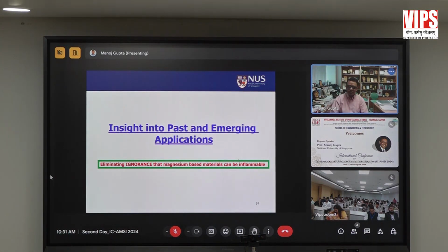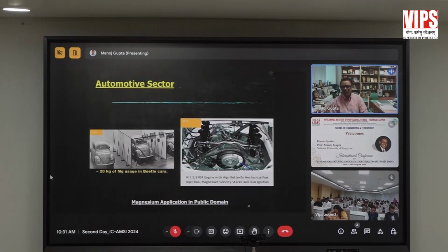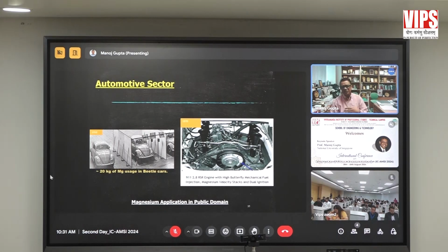Now, people used to say, or were under the impression, that magnesium can catch fire because when we were in school, we used to burn magnesium ribbons and magnesium powder. But that is not true when you use magnesium in the bulk form. And I'll cite certain examples to show how magnesium was used, not only at ambient temperature, but also at elevated temperature. The image you have seen in my cover slide, the Beetle car, uses 20 kg of magnesium. And in the image on the right hand side, you see magnesium used in the engine component.